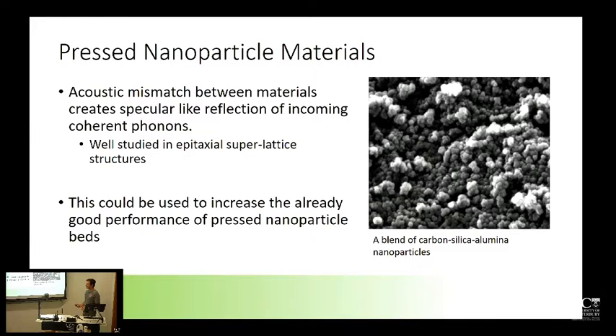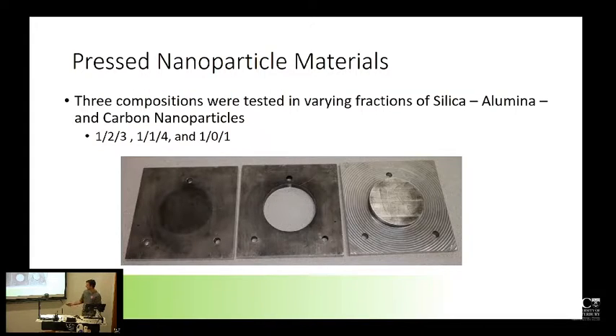Yeah. So the whole idea is we're going to get three different types of nanoparticles, mix them homogeneously together, and then press them into a disk that we could then measure using a few different methods. The first one was called a guarded heat calorimeter, and that's the way you probably measured thermal conductivity for those who were here in undergrad in Phys 101, where you essentially have a fixed temperature on either side and a heat flux sensor in there as well, and then you can measure Ohm's law type stuff, temperature and current in the middle, and you can get a thermal conductivity out of that.